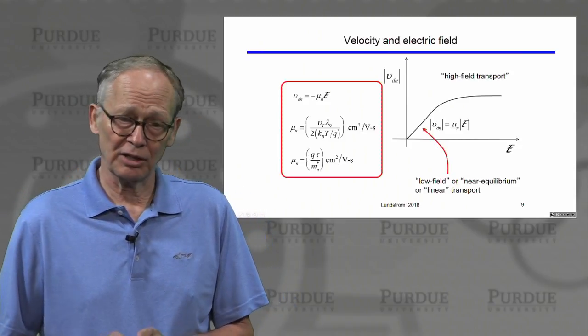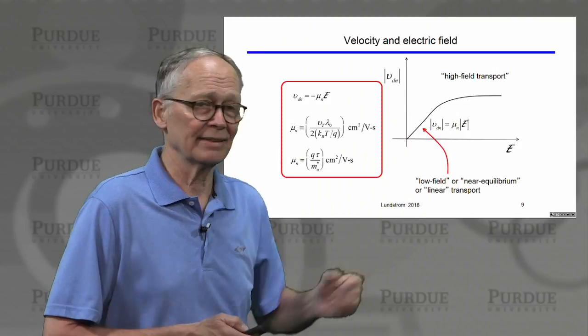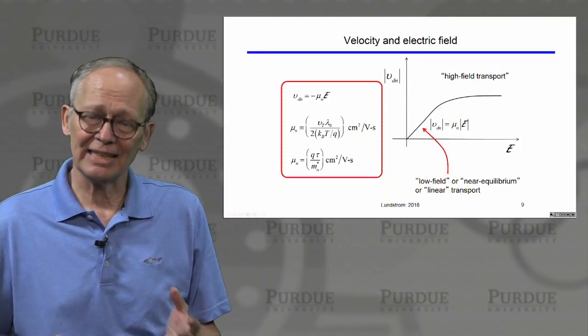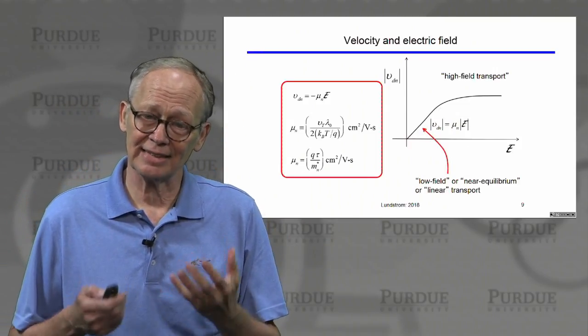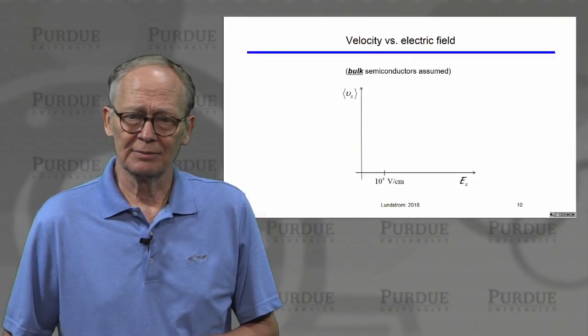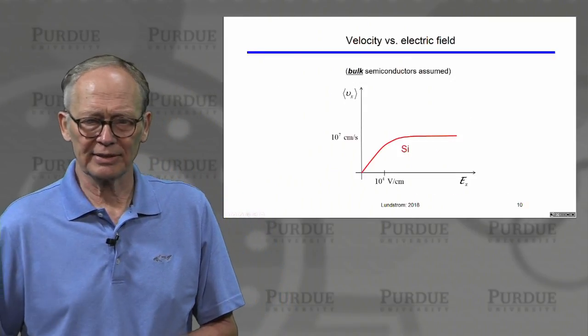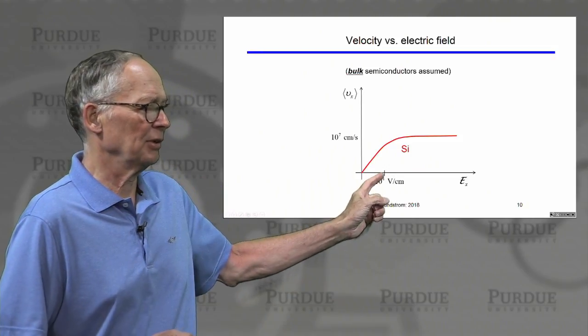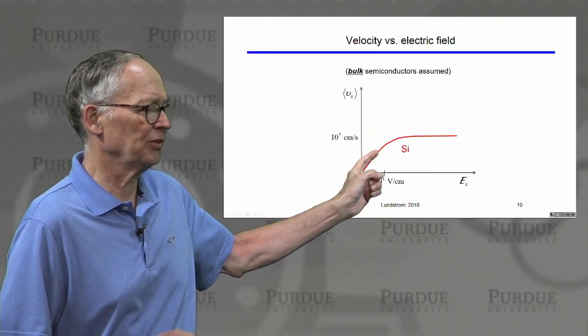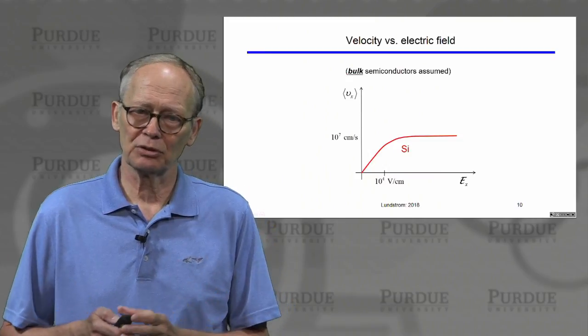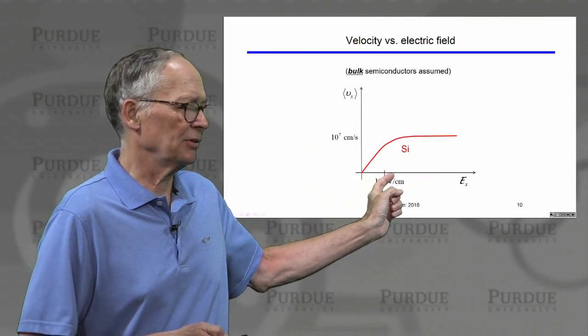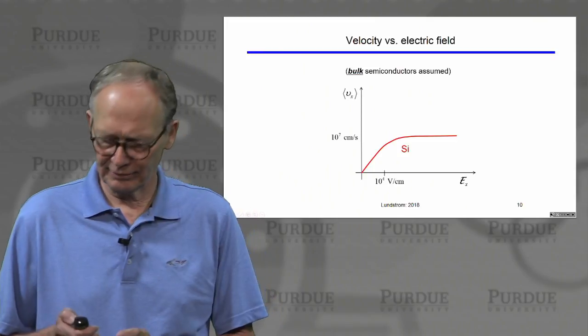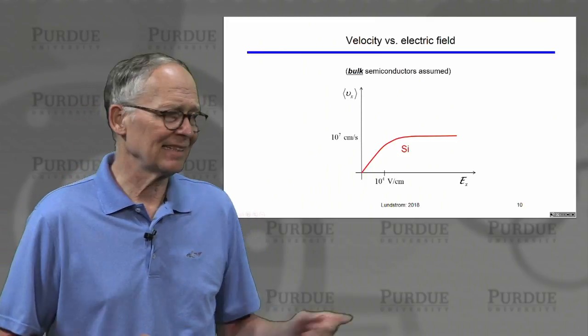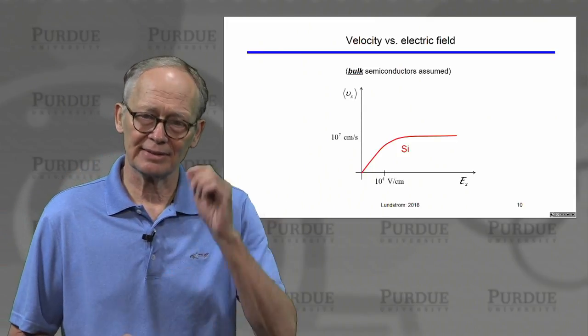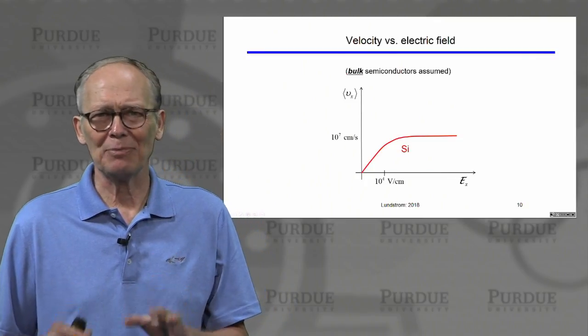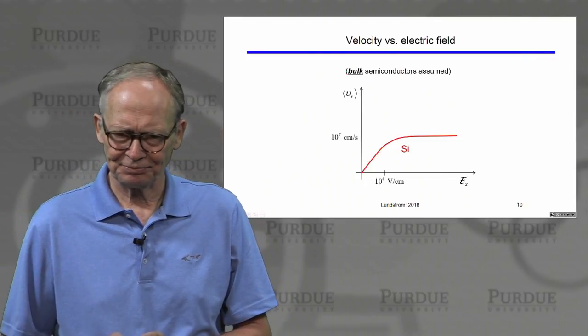But if you apply large voltages, we can see that the current doesn't increase indefinitely. The velocity doesn't increase indefinitely. It tends to saturate at a value. Okay. So if we look at actual characteristics for silicon, we'll see that if the electric field is below about 10 kilovolts per centimeter, the velocity is proportional to the electric field. But if the electric field is significantly higher than 10 kilovolts per centimeter, the velocity saturates at about 10 to the 7th centimeters per second, which just happens to be the average thermal velocity.